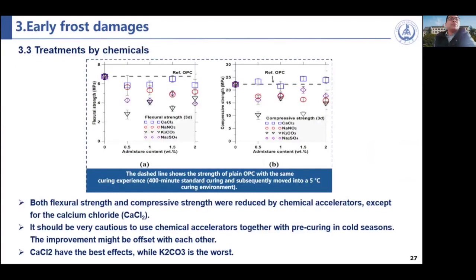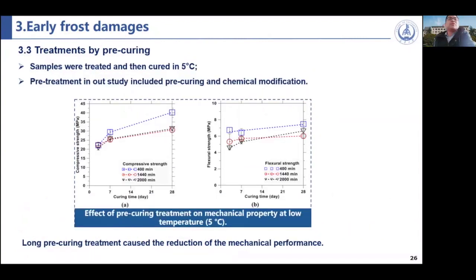We also used chemicals to modify the behavior of the cement at the early ages. We can see both the flexural strength and the compressive strength were reduced by the chemical accelerators, except for the calcium chloride in this. This is also out of our expectation. We always know that salt and most chemicals can accelerate the hydration and the strength development of cement and concrete. However, in this study, we also got a similar result as the pre-curing treatment.